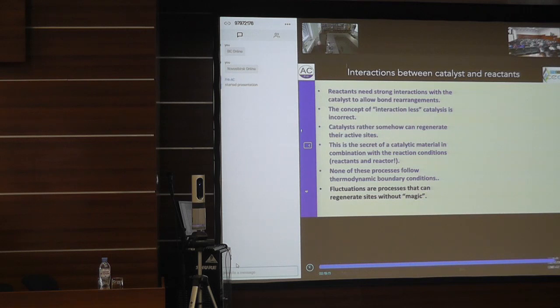The conceptual disadvantage of this idea is, however, that a catalyst has not a fixed number of active sites, and the active sites are not made when you synthesize the catalyst, but the active sites are only coming when you bring the catalyst in this fluctuating state. That means they would not exist outside the operation. And that's another good reason why it is a clever idea to study a catalyst under working conditions, because it might well be that if you do this in vacuum at room temperature, then of course everything is nice and static. And you will see this also later in my presentation.